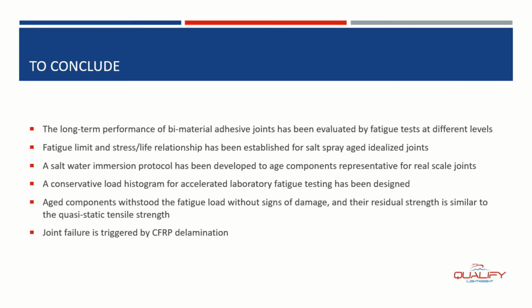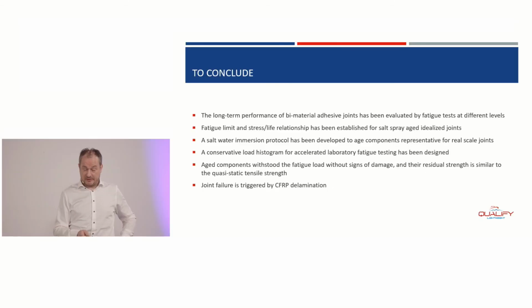We designed a laboratory load histogram for accelerated laboratory fatigue testing, and all the large-scale joints were surviving, I would say, the long-term exposure to environmental conditions and mechanical conditions without any damage in the adhesive. The final failure of these bi-material adhesive joints was initiated by delamination within the composite. And that concludes my presentation.